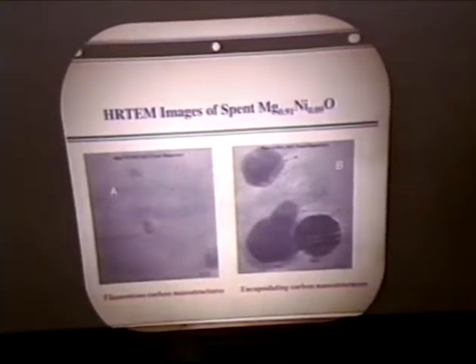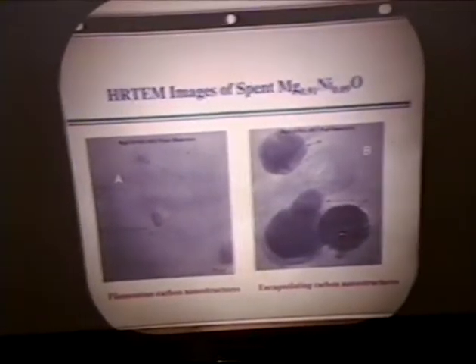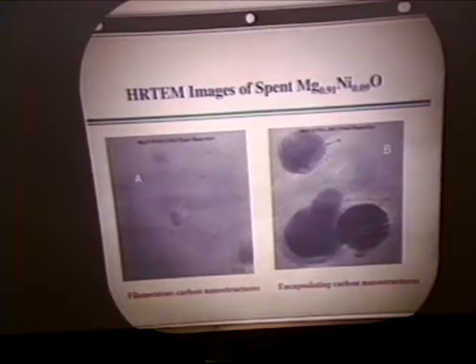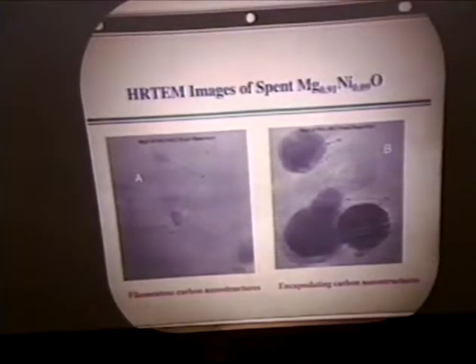Here's the unpromoted catalyst after use. No promoter here, and you can see the nickel particles showing up, roughly 10 to even 50 nanometers in diameter. These particles become humongous. Basically, they come out of the solid solution of the nickel MgO and precipitate on the surface.